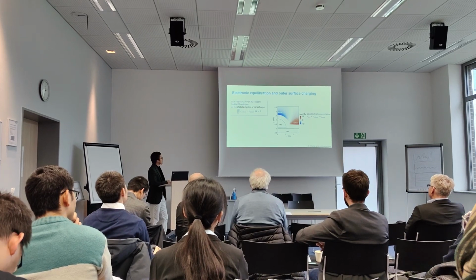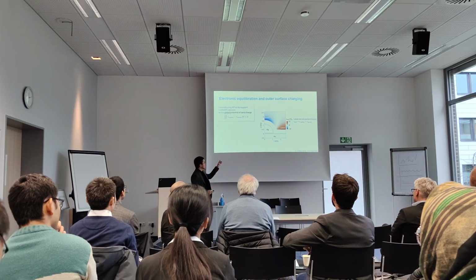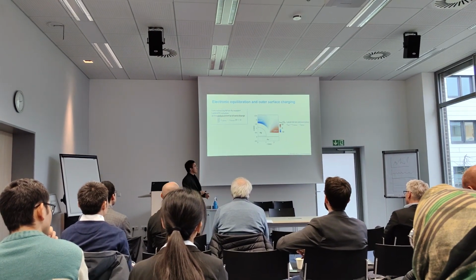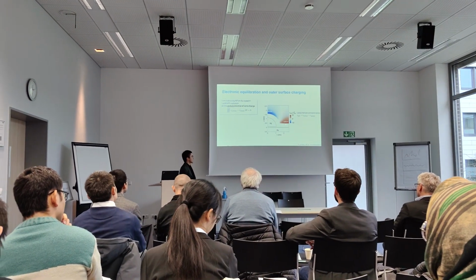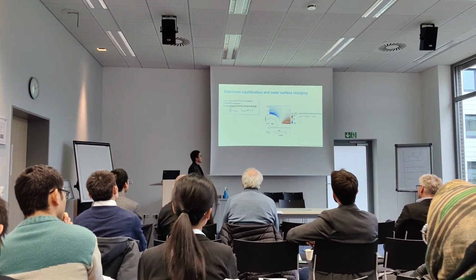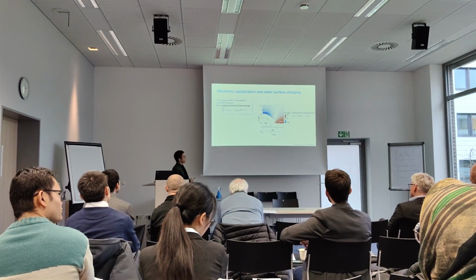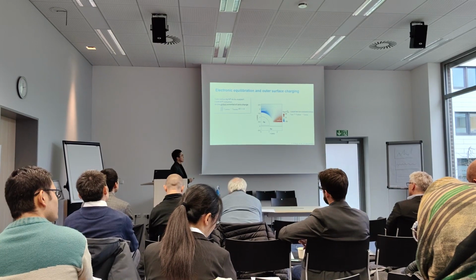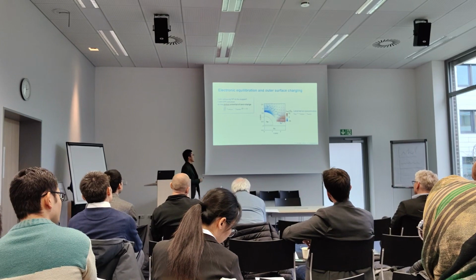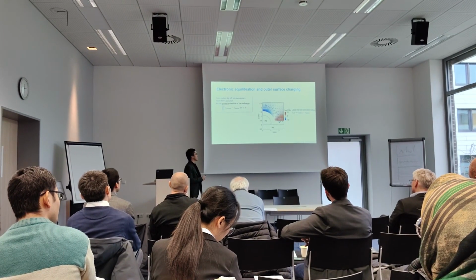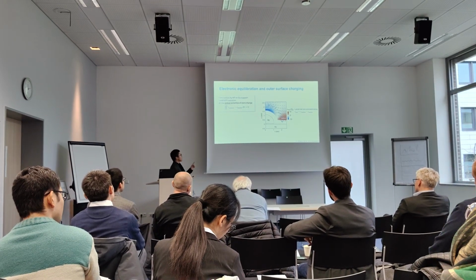And here's what we show. Despite the potential being controlled at the global potential of zero charge, there is charge separation in the solution phase. There are more anions at the silver particle top, there are more cations at the gold surface. That means here the potential is more positive, so anions accumulate. The potential is negative here, so the cations accumulate. And this is evidenced by the electric field pointing from the positive potential region to the negative potential region. And this is a result